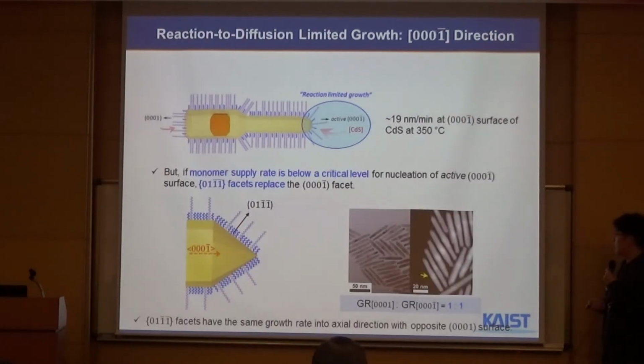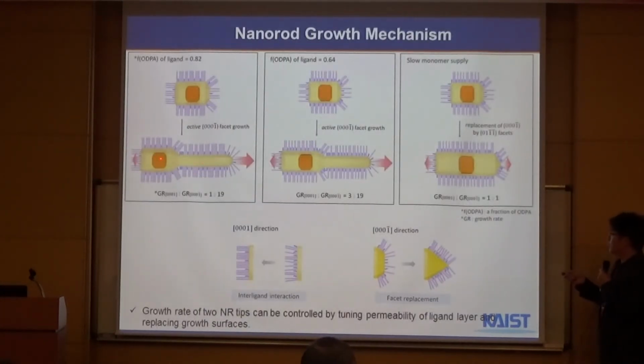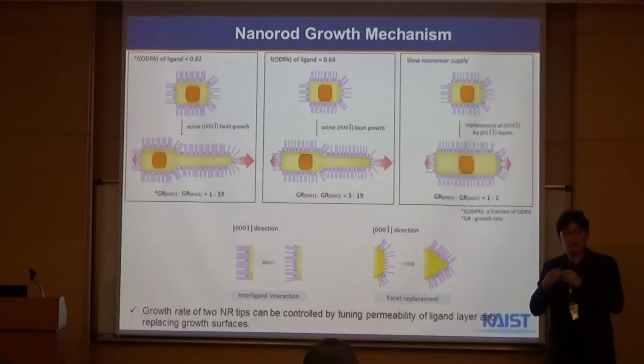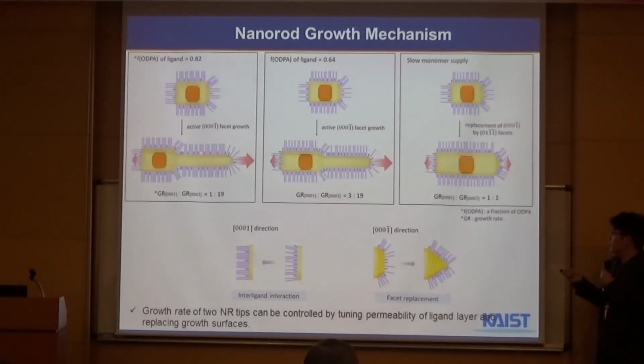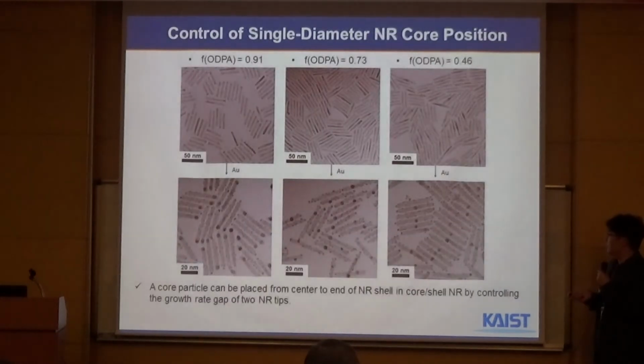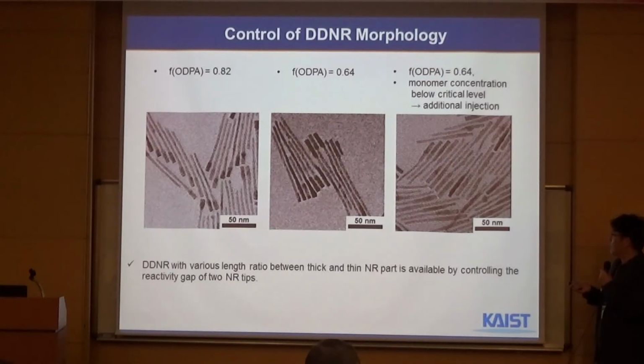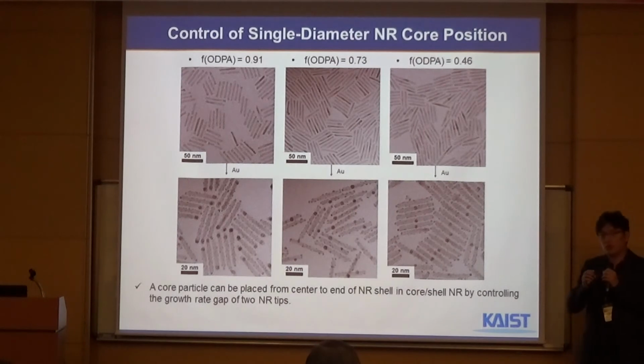Once you do that, now you can change the growth reaction in the 0001 direction versus the 000-1 direction of the nanorods, and you cannot really observe this without having dual diameter nanorod structures like this. And by doing so, we were able to change the core position. So there was a core within this nanorod. You can change the core position by simply controlling the growth rate.